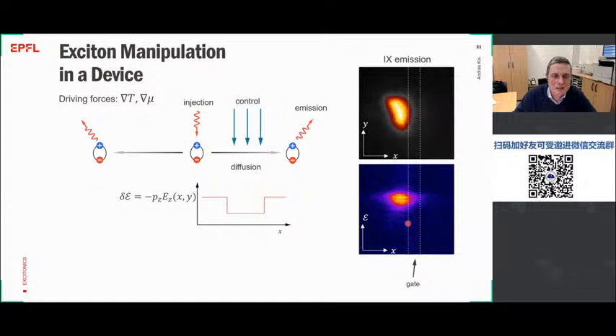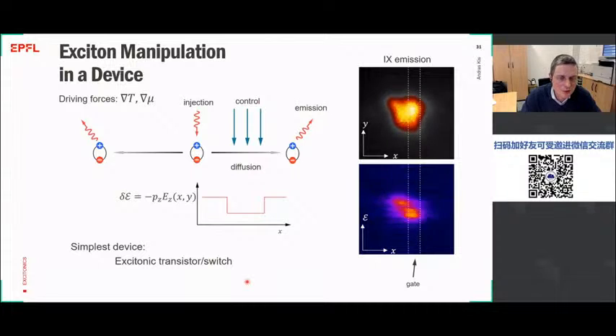And in this second map, we see an energy of the exciton cloud recorded in the same time. So there is a trick with prisms where you can basically take a strip in space of the exciton emission image, and then you can feed that emission to a spectrometer and record the energy. And then here we can see the two clouds. So the first upper energy cloud corresponds to the portion of the exciton cloud which is free. It's not in the trap. And then once a part of the cloud reaches the trap, the energy goes down because the excitons fall into this trap with the lower potential energy. And with this, we can now realize simple transistors and switches, which work on excitons and manipulating currents of excitons and not manipulating currents of single charge carriers.